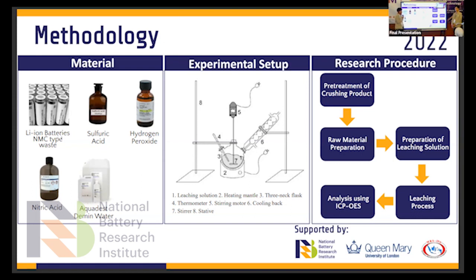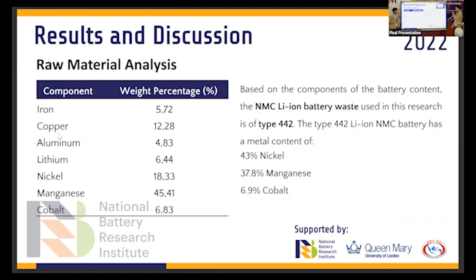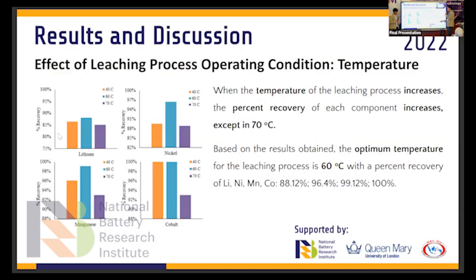The leaching process is carried out at various temperatures and will be sampled at minute 1, 2, 5, 10, and 20. So that is the table of the raw material analysis of NMC lithium battery waste from VR. Based on this table, we can conclude that our waste is categorized as type 442. And then this is the effect of temperature on percent recovery. Based on this graphic, the correlation between temperature and percent recovery is positive, except at 70 degrees Celsius. Why? Because in this phenomenon, we get a decomposition process of hydrogen peroxide. So we can conclude that in our research, the optimum temperature is 60 degrees Celsius.